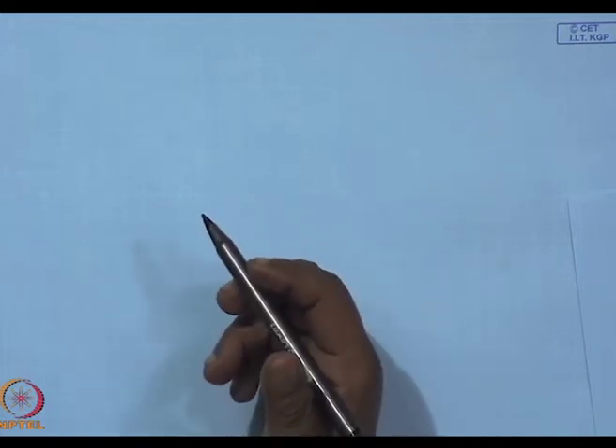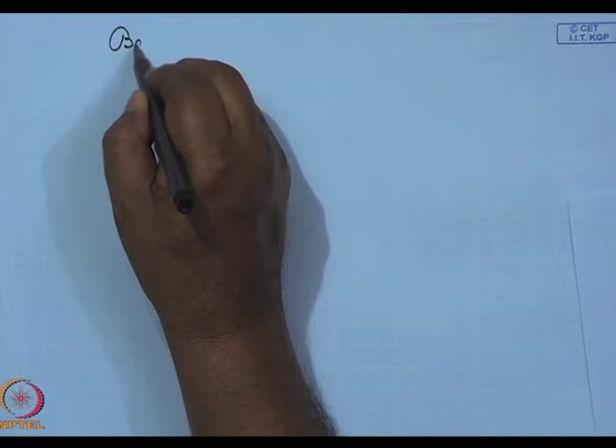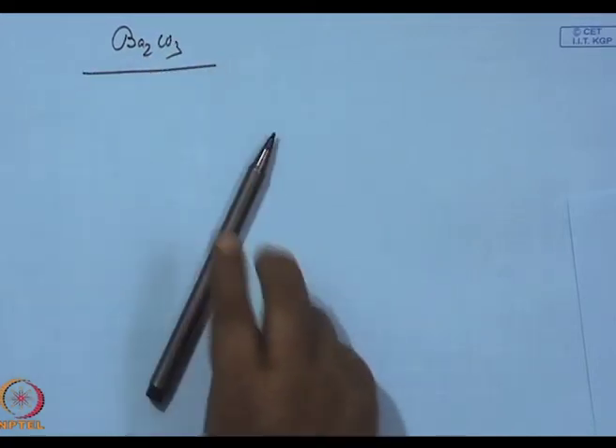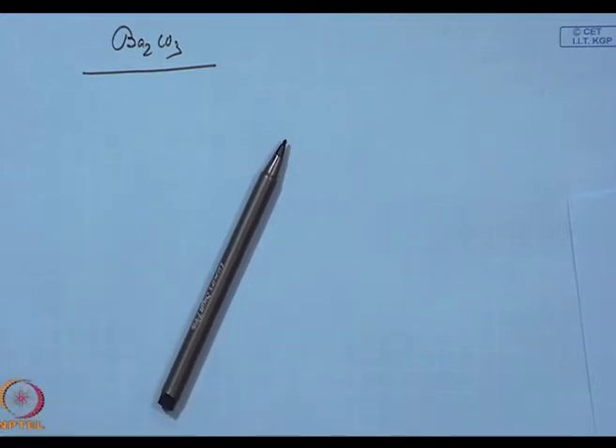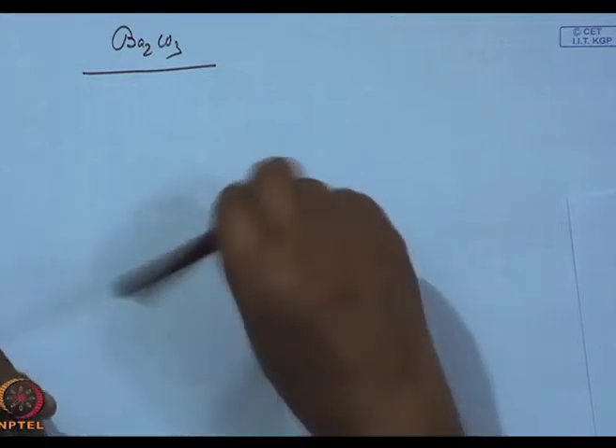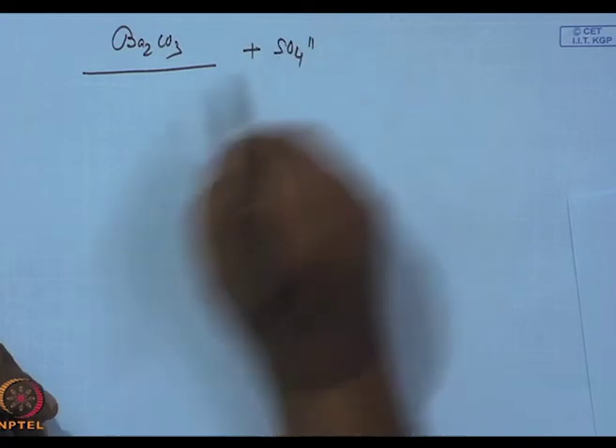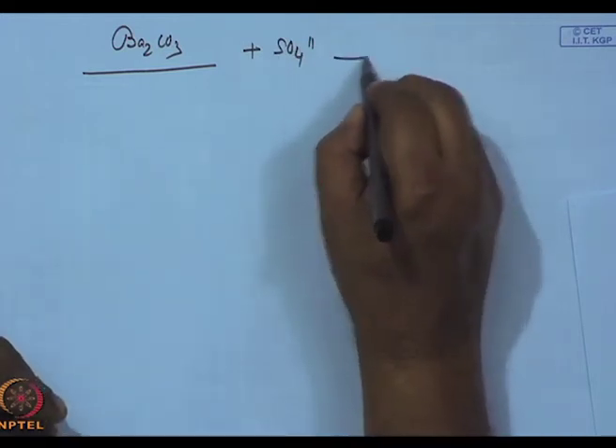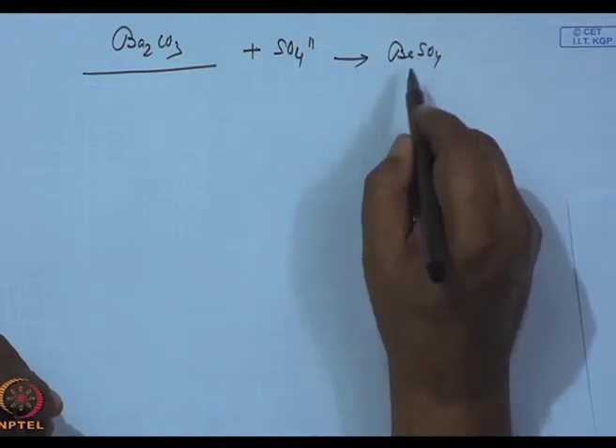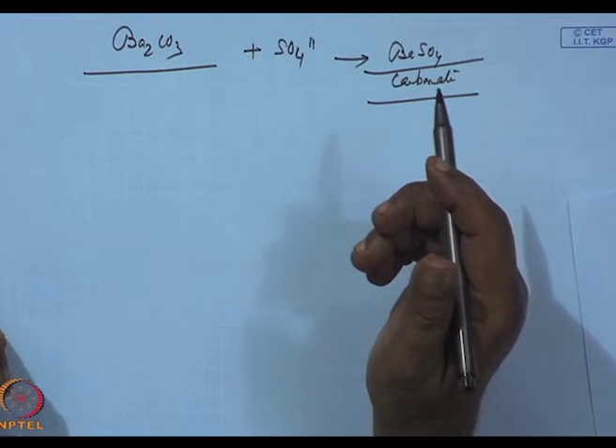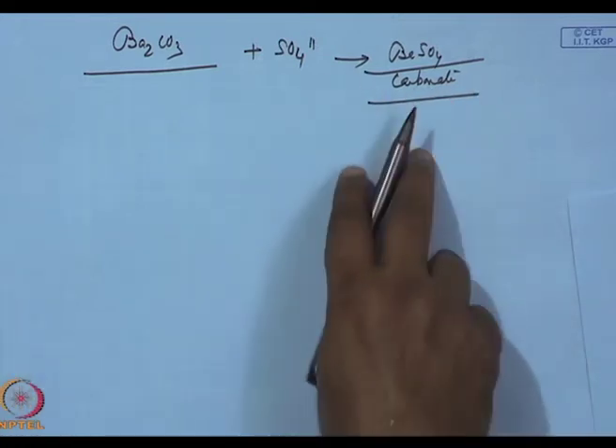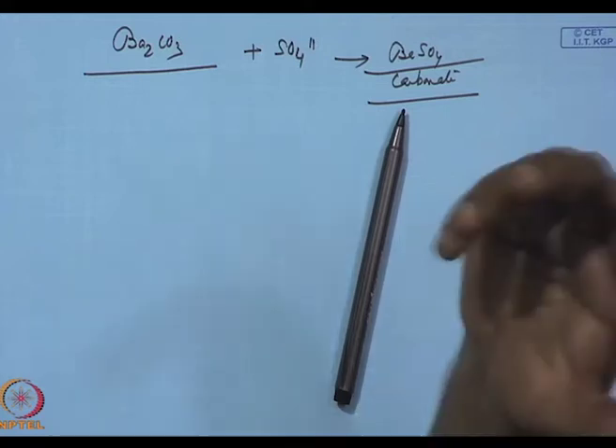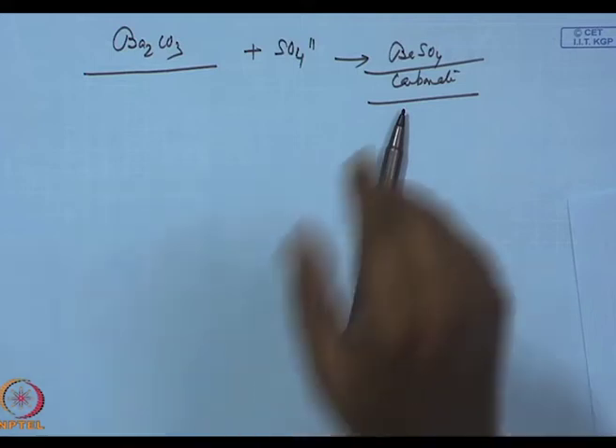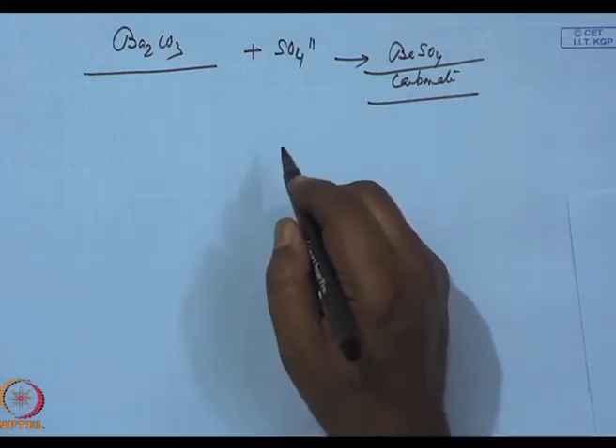Among the other deflocculants which I have not talked of, one is a very interesting one, barium carbonate. Barium carbonate by itself does not cause deflocculation, but there are plenty of sulfate particles in solution. It combines with that, gives you barium sulfate and a carbonate. This barium carbonate acts as a pseudo deflocculant because the carbonate group on barium carbonate is partially soluble, and that is the best way to cause the particles to stay in suspension.